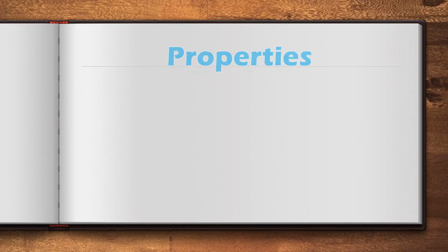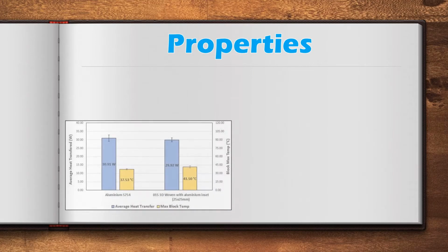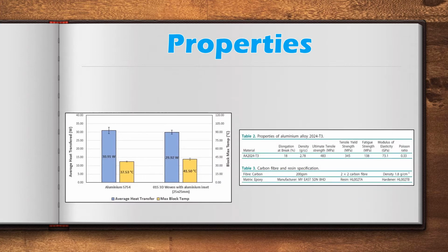This allows us to obtain the best properties of both materials, as we can see in the graph, because we need a high thermal conductivity in order that the heat is dissipated and the box doesn't get too hot. Also, we've found a table about the properties of aluminum alloy and carbon fiber and epoxy. But we found that the average cost of non-space aerospace grade carbon fiber is around $21.5 per kilogram, while aluminum costs just $2.34 per kilogram.